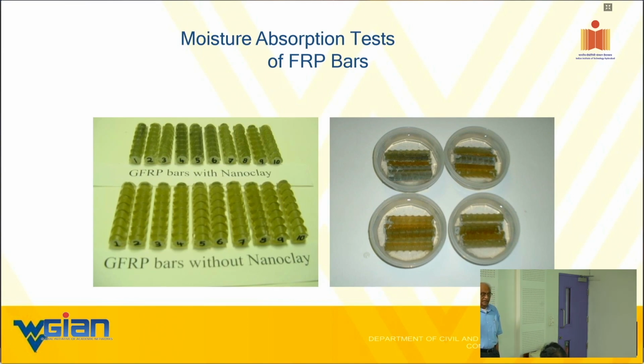As I said, there are two kinds of nanomaterial we used. One is the nano clay, that's the montmorillonite. The other is carbon nanotubes, as an additive in the resin. The toughest part of using a nanomaterial is exfoliation of the material. It's not easy. How do you exfoliate from the standpoint of agglomeration of the material? How do you disperse the material? That is called exfoliation.